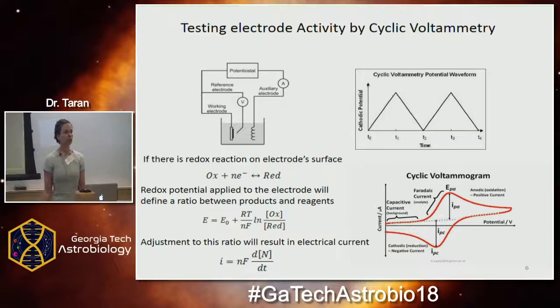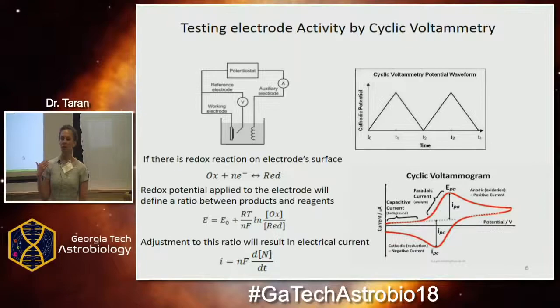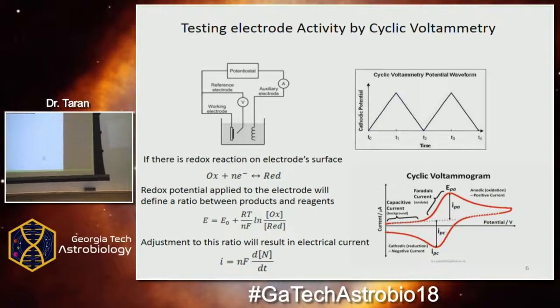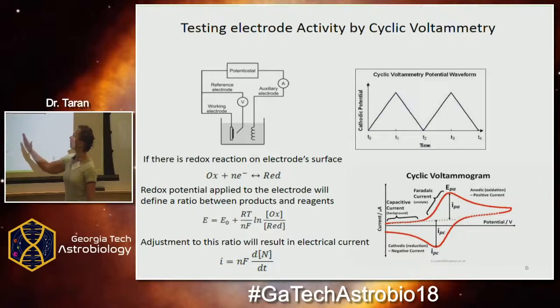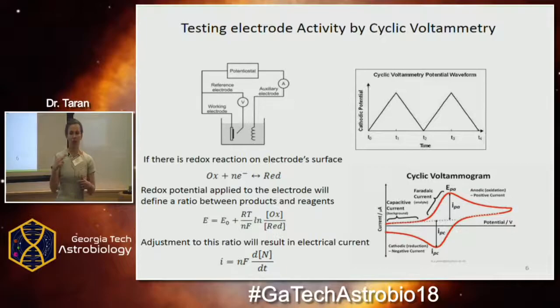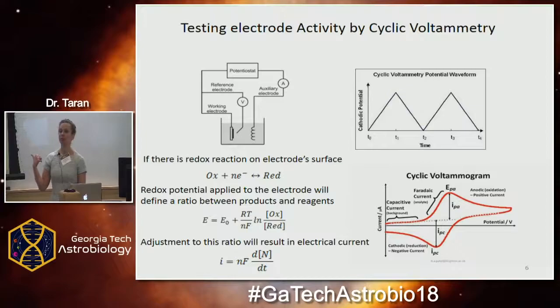To find the ideal mineral electrode, we use a technique called cyclic voltammetry. If you have a redox reaction on the surface of the electrode, electrons are exchanged between the molecule and the surface, resulting in electrical current. By slowly changing the redox potential on the surface of the electrode according to the Nernst equation, you get a current with a maximum around the potential corresponding to the redox reaction of interest. Basically, we went to the museum, asked for minerals, made them into powder, made electrodes out of them, and tested whether they react with organic molecules.